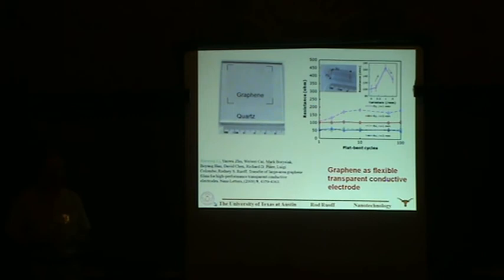Samsung is particularly focusing on scaling up the material. They are closely allied with that Korean university group that published that other paper in Nature Nanotechnology on transparent conductive electrodes for plastic electronics. So it's possible that you'll see these just within a few years on actual consumer electronics. Our group had published on that actually before they did, and Shusung Lee, in a very challenging experiment, would grow monolayer graphene on copper, dissolve the copper, transfer it over to a quartz substrate, and then grow another monolayer and transfer that on top, and so on until he had up to 4 layers.